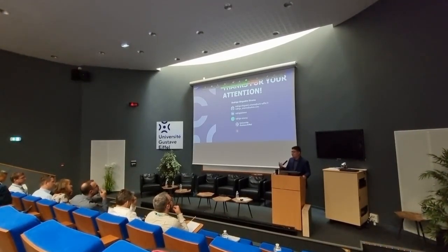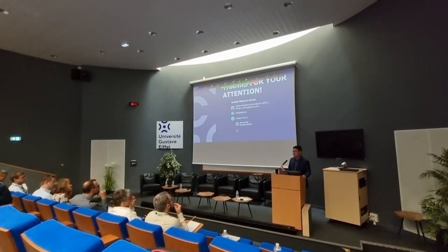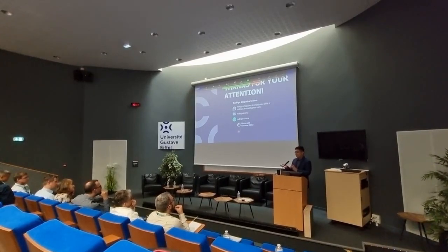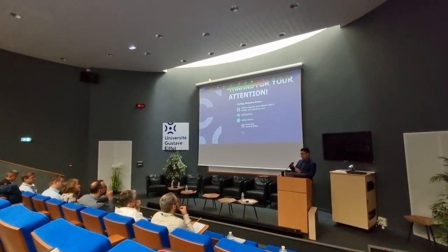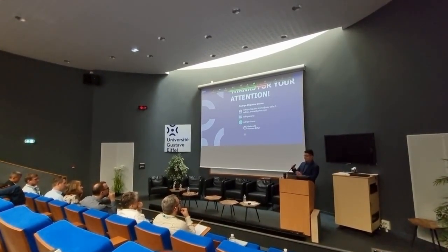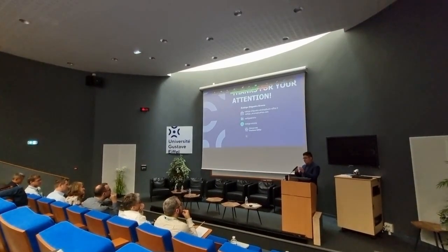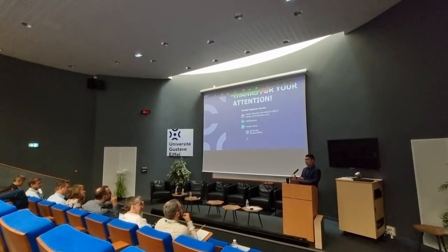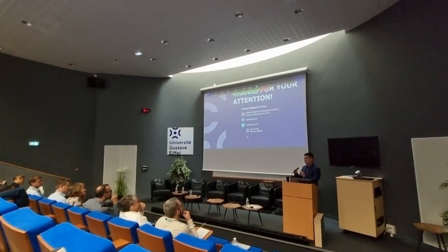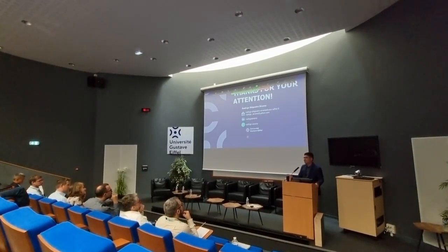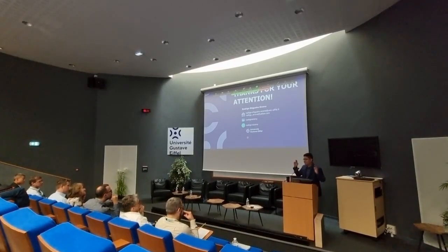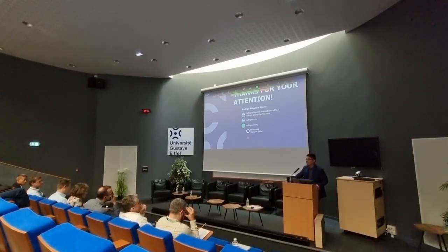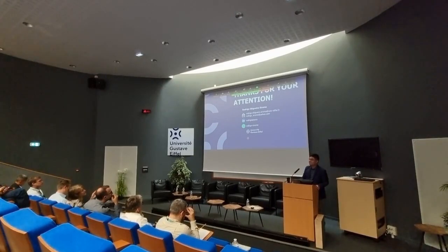But then we ran the test again and we got the same results. And just to be sure, we took just the bottommost layer and cut it in the middle, and we found that the bottom of this layer was more rigid than the top part of this layer, which validated our observation of this inverse aging gradient. It is interesting.